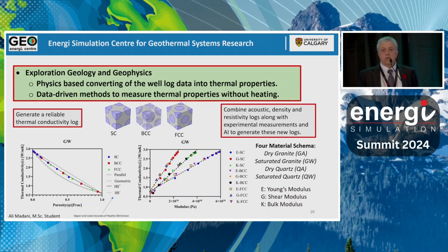And we found that material properties from acoustic measurements correlate well with thermal conductivity, and we got some really cool correlations with granite and quartz type of geometries, dry and saturated. So looks promising. I most likely have something more interesting to give you next year on that.